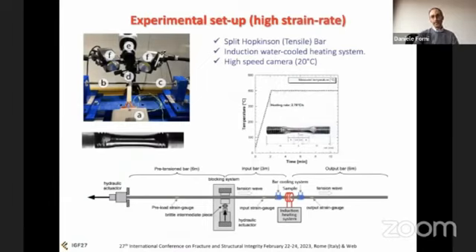The dynamic characterization has been performed by using a modified Hopkinson tensile bar plus the addition of an induction water-cooled heating system, as you can see on the image. The tests were performed firstly by heating the sample at the desired temperature, and then by keeping the temperature constant for some seconds or minutes, and then performing the dynamic test.